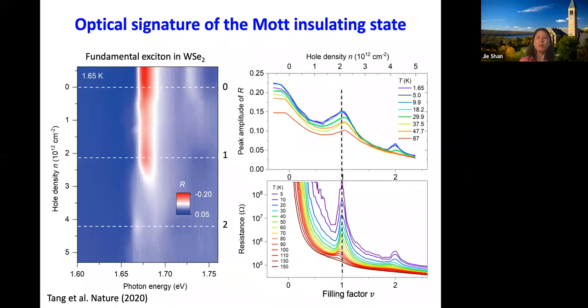So I would like to return to this picture a little bit. I presented this transport result to show that we have a resistance peak at half filling, or nu equals 1. But unlike those beautiful transport works from graphene, we actually suffer quite a lot, especially at low temperature for low filling factors. And that's because of the contact. And it's sort of intrinsic because we are dealing with large gap semiconductors.